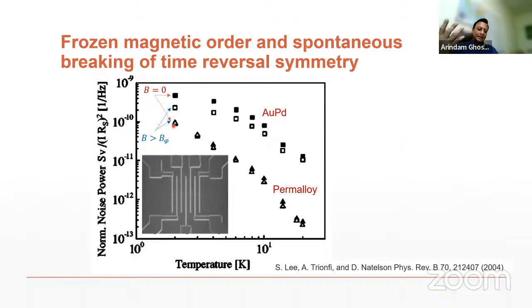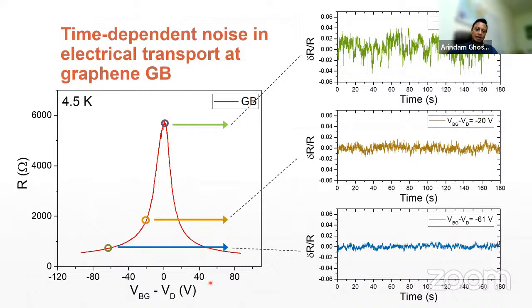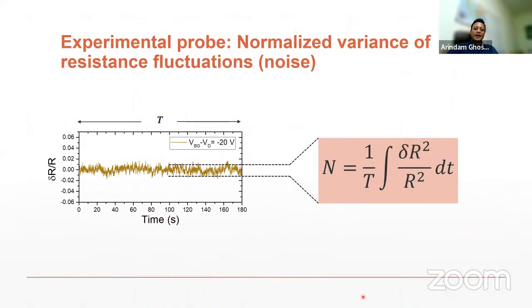So here is a typical graphene grain boundary, resistance versus gate voltage. You can see exactly the same as the graphene transfer characteristics that I showed you earlier, the large noise in the Dirac region. And as you increase the gate voltage, the noise comes down. And our experimental probe is the variance of noise. So if I take the delta R by R and I take the variance of these fluctuations, then this N is the noise, which is the integrated fluctuations over a certain time t, is our experimental probe.